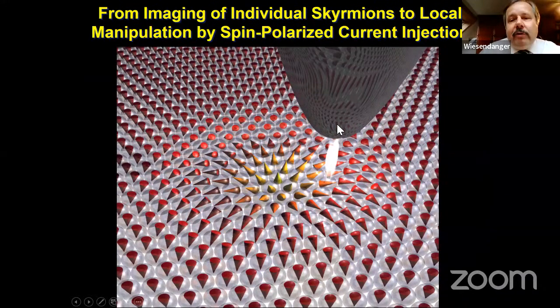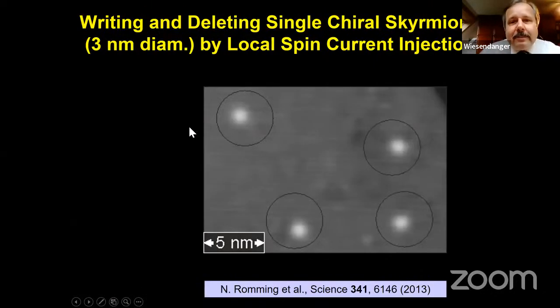Why? Because if you increase the spin current density, you can exert a considerable spin torque on your magnetic layer, which allows you to destabilize the ferromagnetic state. And you can create either stable skyrmions in a metastable ferromagnetic background, or you can create metastable skyrmions in an otherwise stable ferromagnetic background. You see that indeed this works out experimentally.